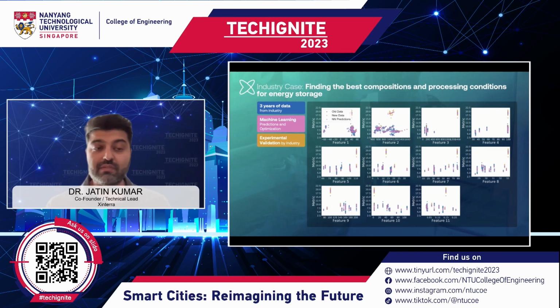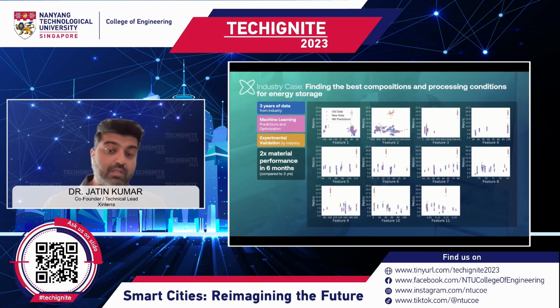Again, 3 years of work on this, and we achieved this in 6 months. We doubled the performance in 6 months. What you don't see in this deck of slides was that we also predicted that there was a possibility of tripling the original performance and going up to a metric of around 30. Of course, at that point, the project ended and we didn't proceed any further. But really, the AI could continuously keep optimizing up till the actual physical limit of the system that is bound by the thermodynamics of the system that you're in, rather than settling for what is good enough for now.